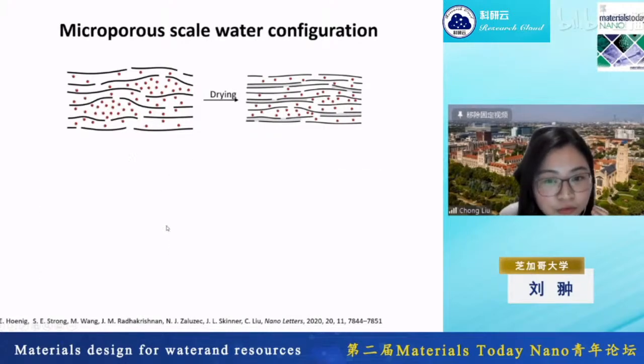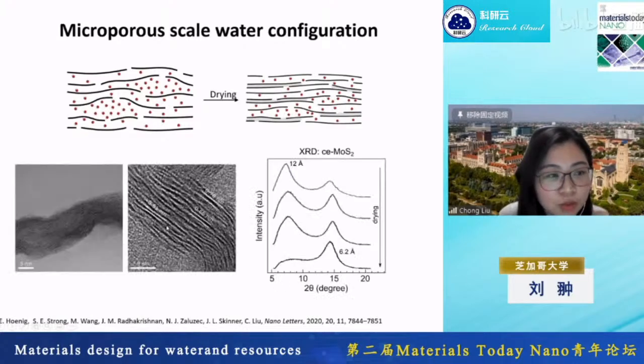But if you dry up the membrane to decrease the big water pockets, and you keep drying, what happens is that you create a lot of dead ends in the membrane. From these microporous scale features, the XRD shows you that the wet layer spacing, the sweet spot spacing, is 1.2 nanometer. But if you remove all the water, it goes back to its bulk crystal lattice spacing, which is 6.2 Angstrom. You can also see this in the cross-section TEM of the membrane.